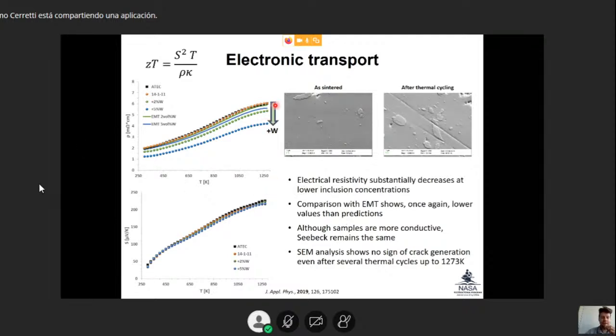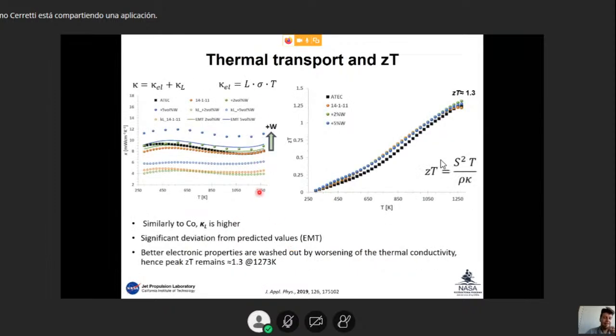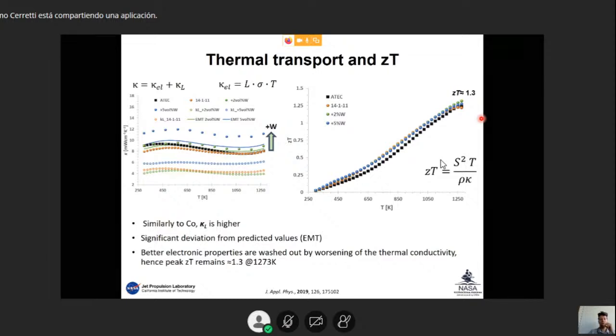Surprisingly, with this big reduction of the electrical resistivity, there was no reduction at all of the Seebeck. Seebeck remained constant, and that's a very positive thing for the transport. But then, for this tremendous reduction of the electrical resistivity, we paid in the thermal. So the thermal conductivity increased, therefore canceling out the positive improvement on the electronic transport, and in the end the ZT remains pretty much the same, because ZT is about 1.3.